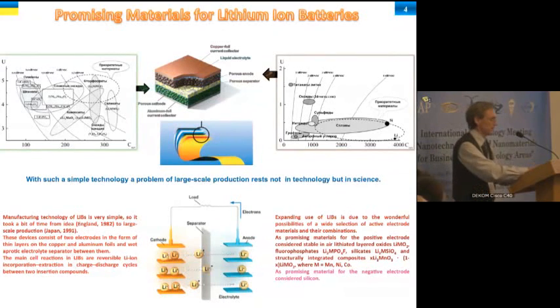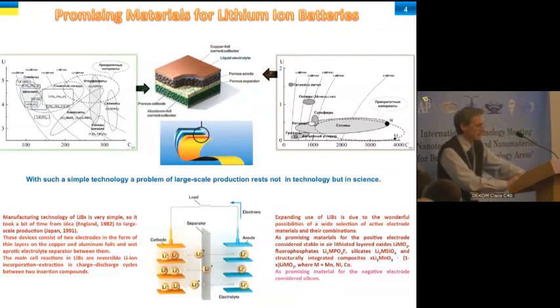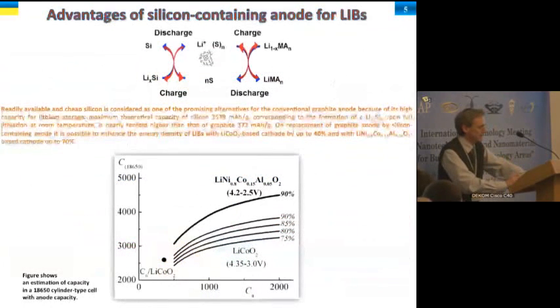On replacement of graphite anode by silicon-containing anode, it is possible to enhance the energy density of lithium-ion batteries with traditional lithium cobalt oxide cathode by up to 40%, and with new lithiated nickel cobalt aluminum cathode up to 70%. Using nanosilicon leads to better cyclability than in the case of microparticles.